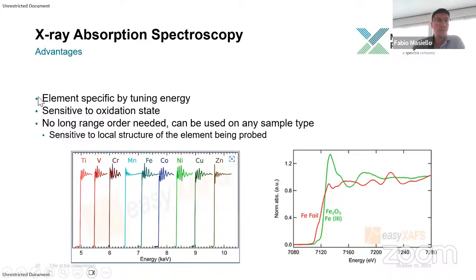As you can see here, it's element specific. It's possible to tune in the energy. So for example, from titanium, vanadium, chromium, etc., you can see that the edges are different. So you can actually look at the environment around a specific element in your sample and not so much the other environment. It is also a technique that is sensitive to the oxidation state, as it is shown here.